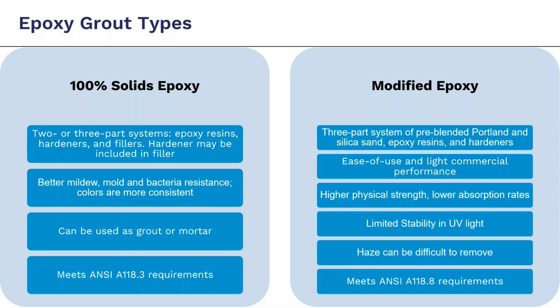And then it does meet the ANSI 118.3 requirements. With a modified epoxy, it is a three-part system of a pre-blended Portland, silica sand, epoxy resins, and hardeners. It's easy to use and is good for light commercial performance. It's higher in physical strength, lower in absorption rate.